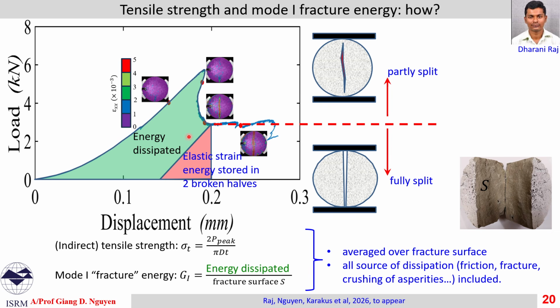We can work out the mode 1 fracture energy by this: the energy dissipated divided by the fracture surface S, which can be worked out from the broken specimen diameter and thickness of the specimen. So if that is successful, we can work out two important properties: indirect tensile strength and mode 1 fracture energy.